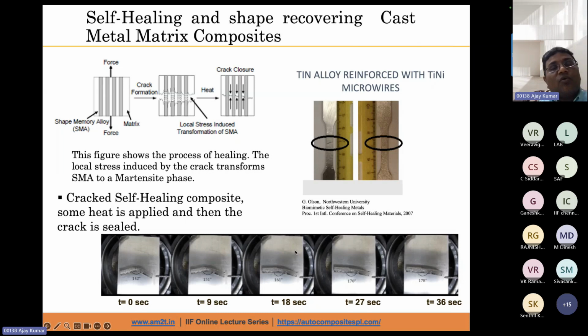Another recent trend which is now going in the area of MMC is because a lot of work has been reported in the area of particle reinforcement composites, especially in the aluminum matrix, aluminum alloy, magnesium alloy, copper alloys. And now the recent trend is going in the area of self-healing and shape recovery cast metal matrix composites. So this concept will help a lot, especially in the crucial applications or even civil military vehicles applications. So if any crack nucleates during the operation of any component, and once the crack nucleates, it propagates very fast. So we have to see if we can stop the propagation, if not 100%, at least some extent. So that is how the self-healing and self-shape recovery concept will help.